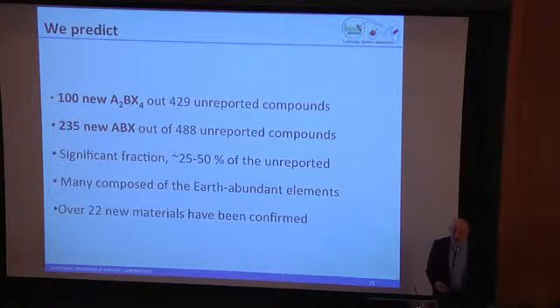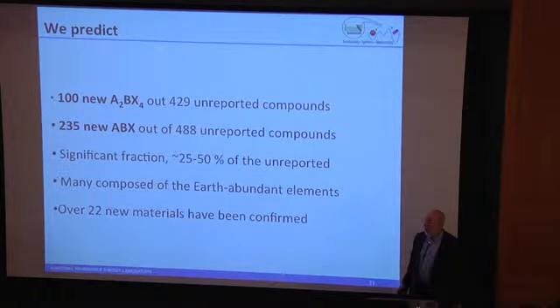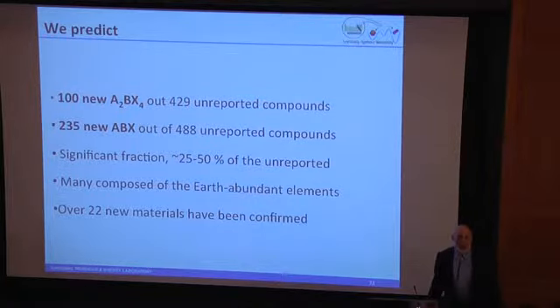So for example, we made the tantalum cobalt tin. And you would have looked at that and gone, oh, a metal alloy. Who cares? It's boring. Well, it turns out that tantalum cobalt tin has a band gap of about 1.7 eV. And actually looks like it might be a very interesting solar absorber, even though it's all metal. And so there's a lot of interesting materials, properties.